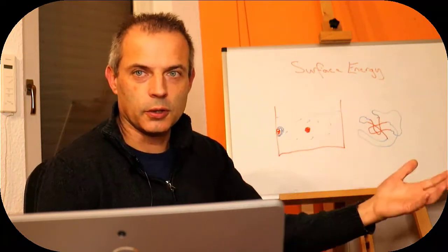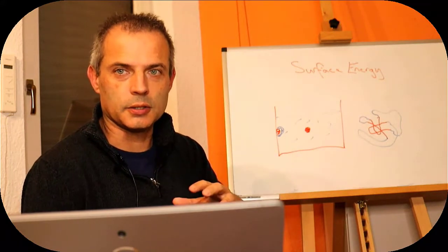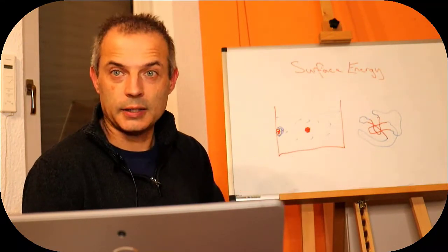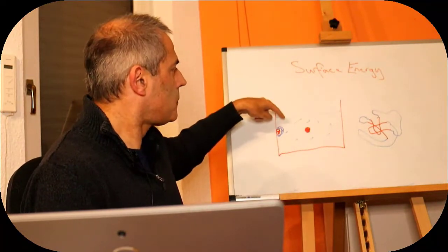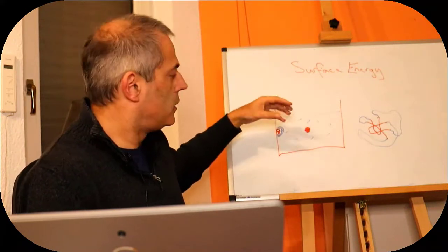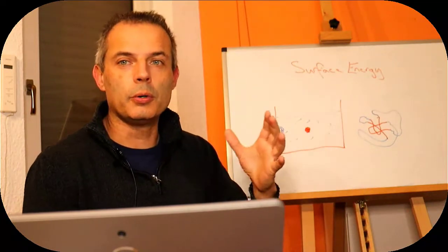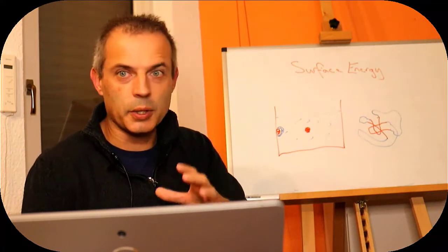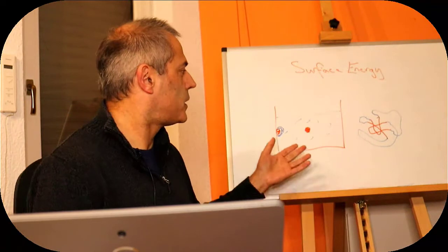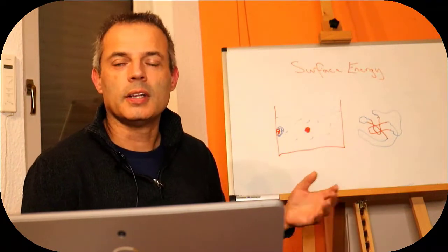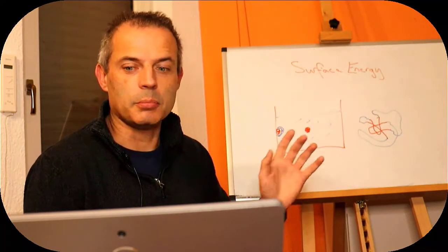This protein can stick on and let go, but there's a question as to how damaged it is when it goes back into the solution. It depends. Very often it can. Albumin can usually refold, other proteins often can't. What that means is that we have a stickiness from our protein to both hydrophobic low energy surfaces and hydrophilic high energy surfaces, but if they are somewhere in between, like water, then it's not so sticky, and that means we end up with the following type of behavior.